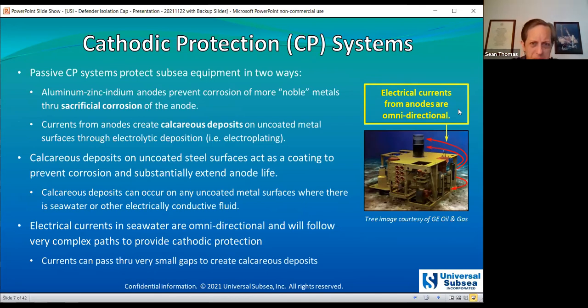Many of you will be familiar with cathodic protection systems. More than 90% of the CP systems used for offshore equipment are passive systems that use aluminum, zinc, indium alloy anodes. These prevent corrosion through sacrificial corrosion of the anode. This creates an electrical circuit, so we have currents flowing through the seawater from the anodes to what's known as the cathode, the materials being protected by the anodes. And this is an electrolytic deposition process, basically electroplating.